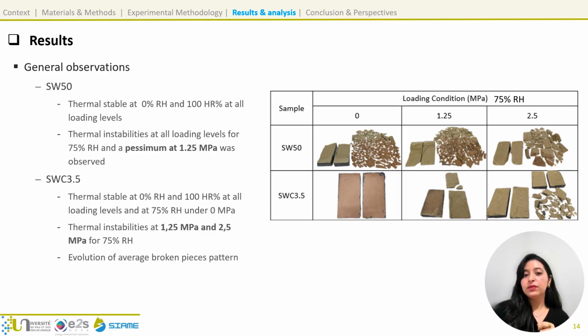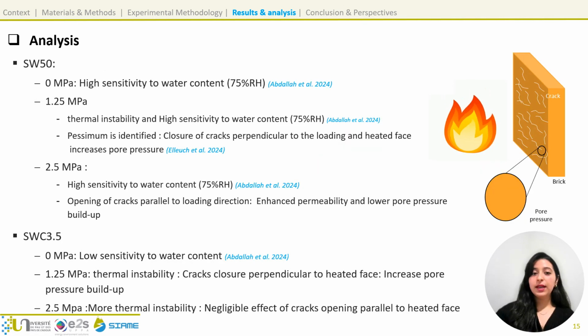As shown here in this photo, at 75% relative humidity, spalling is much more severe in SW50 than in SWC 3.5. Moreover, for SW50, fragmentation is higher at 1.25 megapascals than at 2.5 megapascals, which is the maximum effect. Whereas for SWC 3.5, the opposite trend occurs with more broken pieces at 2.5 megapascals. Now we will analyze the behavior of both brick types.